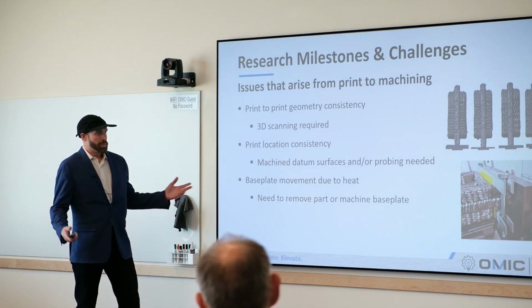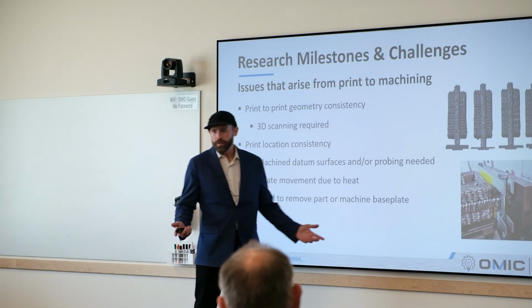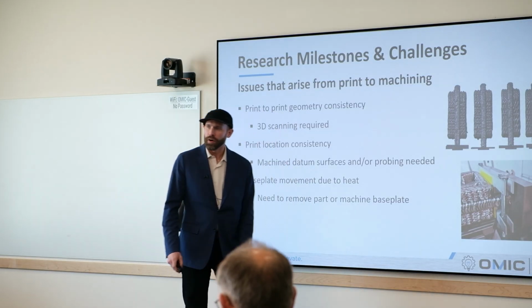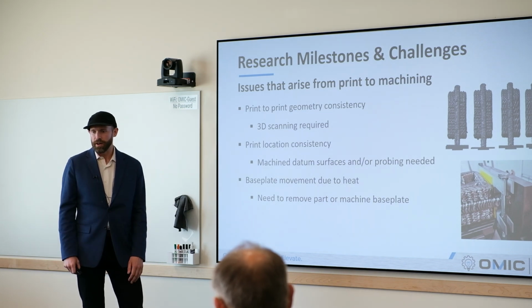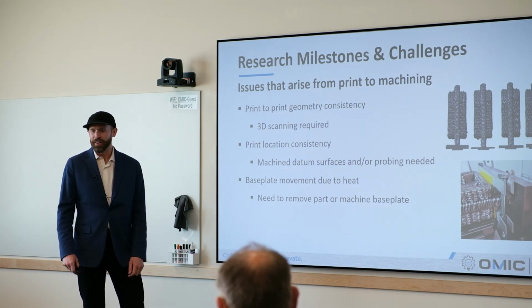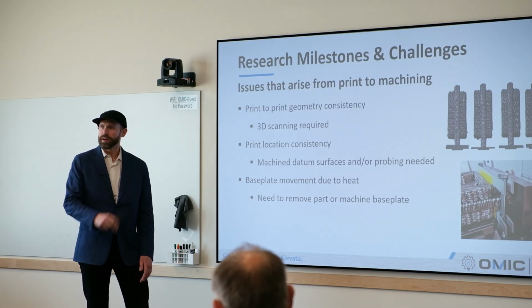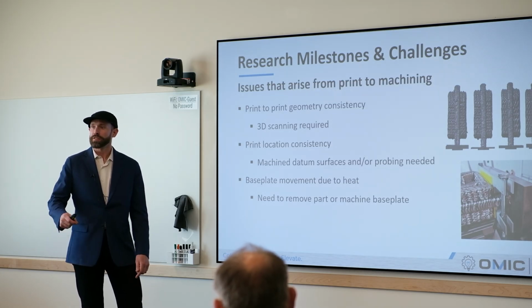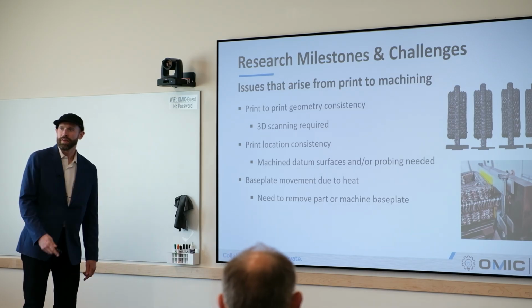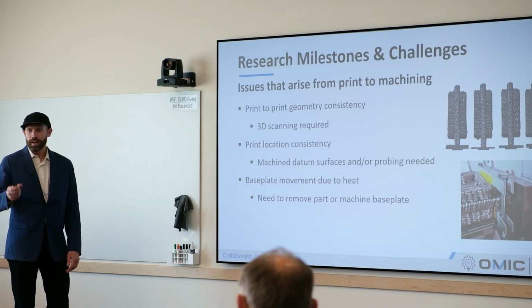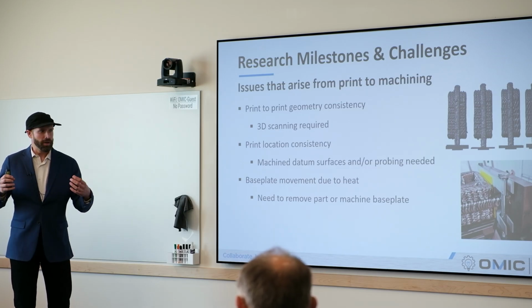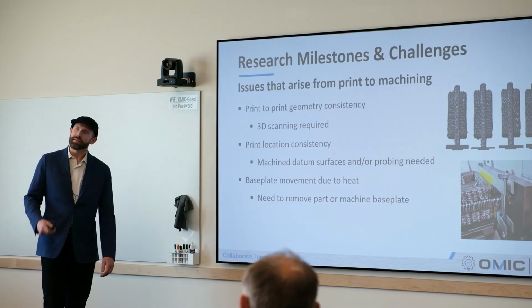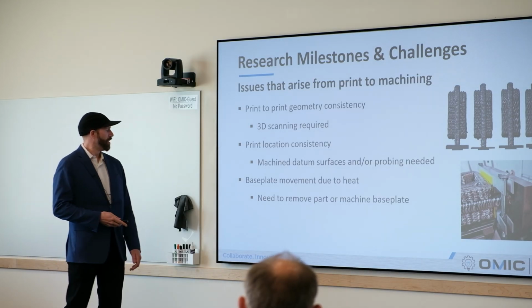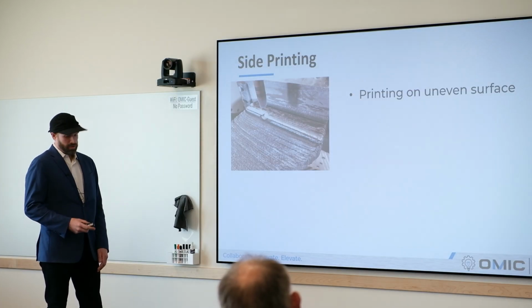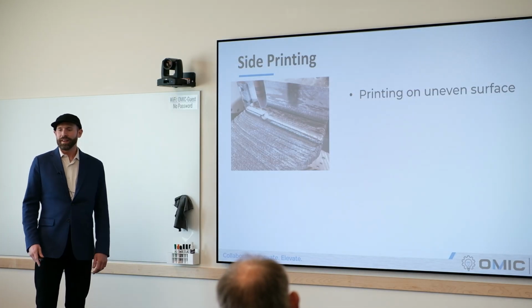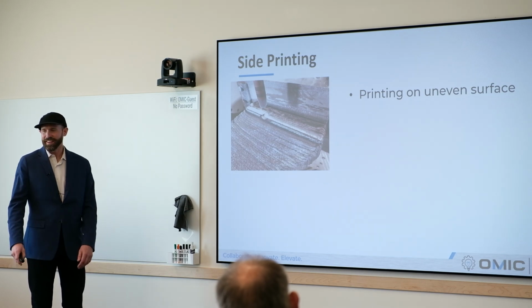And then sometimes the base plate just moves so much that you have to remove the part like we are doing with these incoming plates, right? We don't want to machine these base plates down half an inch just to flatten them out. We'd rather just wire EDM the part off and then build a fixture based on the geometry we built into the print. And that geometry being built into the print can be more uniform based on a bunch of different part designs, right? So that's more ongoing research in itself.